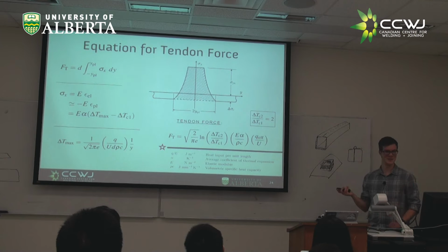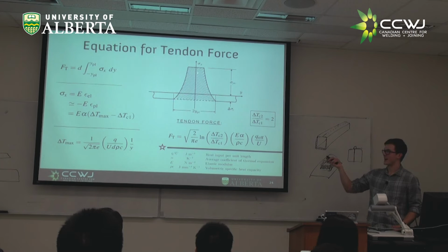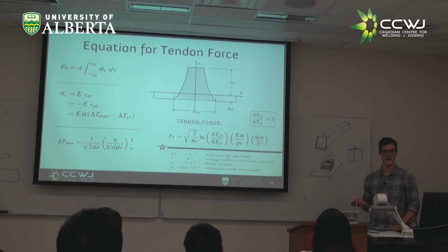We didn't have to do any simulations though. One integral you could have done after first year calculus, and you see that although the magnitude gets higher, the yield stress gets higher, each of these values individually gets higher, the ratio stays the same, and so we don't have higher residual net force. Does that make sense to everyone?